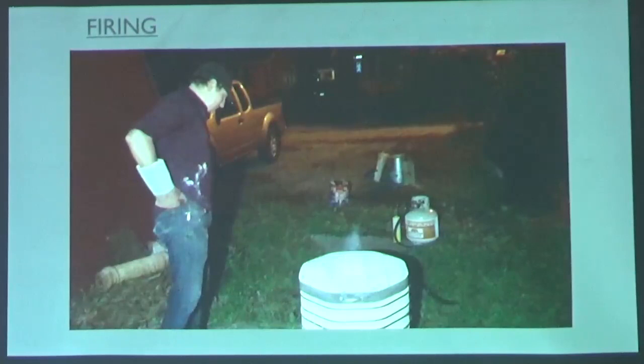Yeah, physical water leaves between the boiling point, 212, and about 350. That's when you see a lot of steam coming out of the kiln, and you get an interesting smell. Then chemical water starts burning off at around 600 degrees. That's water actually in the molecules of the clay. That's what causes a lot of the shrinkage too, the water and the organic materials burning off. Then after that you get sulfur burning off, which creates a really neat smell. The neighbors love it. And yeah, as Eric said, you have to do this really, really slowly.